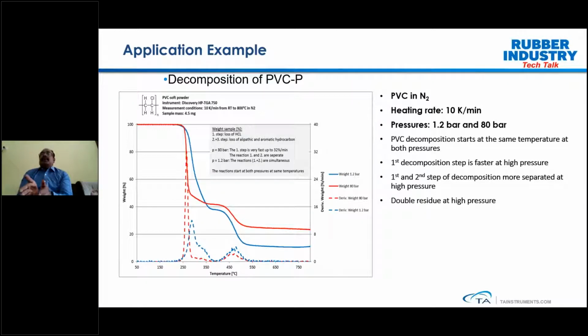Now, the same studies we are doing at an elevated pressure, which is at 80 bar. So what we see here is you can see clearly the onset of reaction at the same temperature, but the studies which we have done at the 80 bar show the faster decomposition rate as compared to the studies that we performed at the lower pressure. So this clearly signifies how pressure actually speeds up the decomposition process.